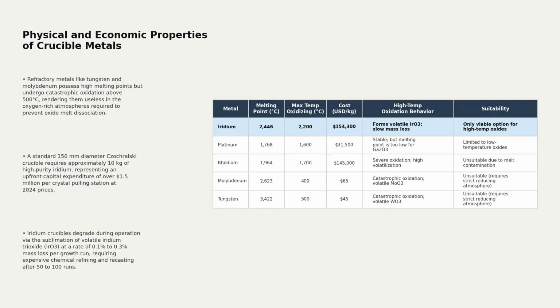A standard 150 mm crucible requires 10 kilograms of high-purity iridium. At 2024 prices, this represents an upfront capital cost of over $1,500,000 per station. Furthermore, these crucibles degrade via chemical sublimation, losing up to 0.3% of their mass per run. This degradation forces operators into frequent, highly expensive chemical refining and recasting cycles.